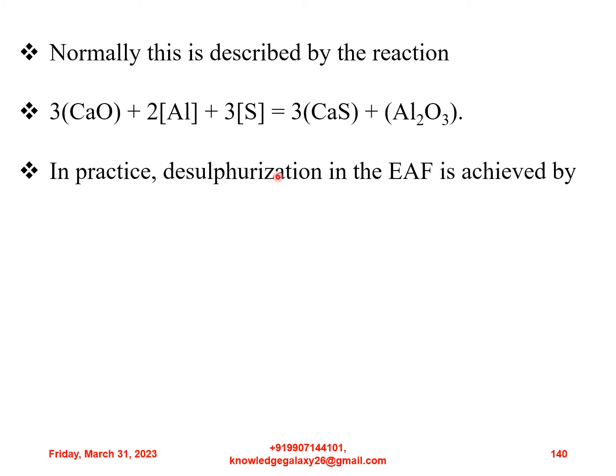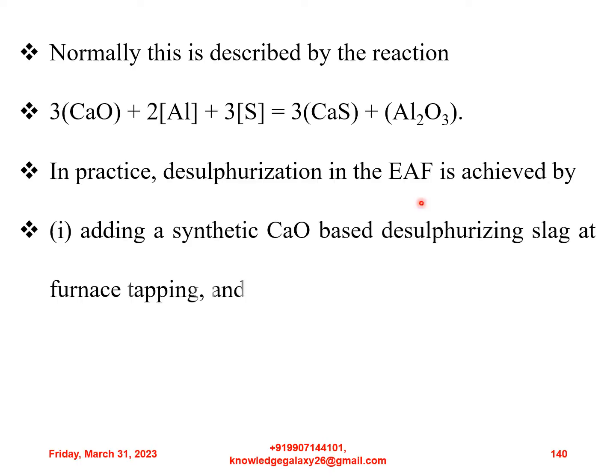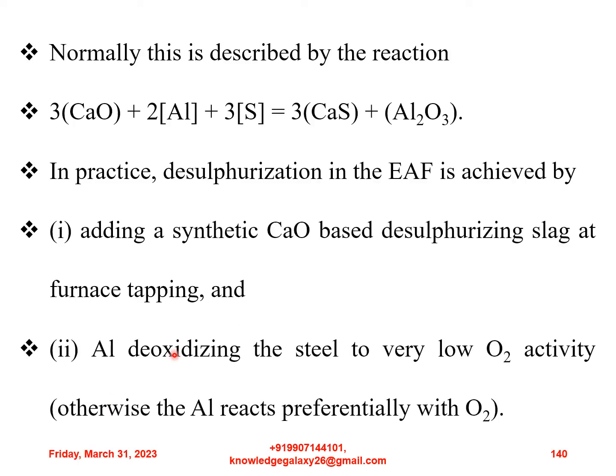In practice, desulfurization in the electric arc furnace is achieved by first adding a synthetic CaO-based desulfurizing slag at furnace tapping, and next aluminium deoxidizing the steel to very low oxygen activity. Otherwise, the aluminium reacts preferentially with oxygen.